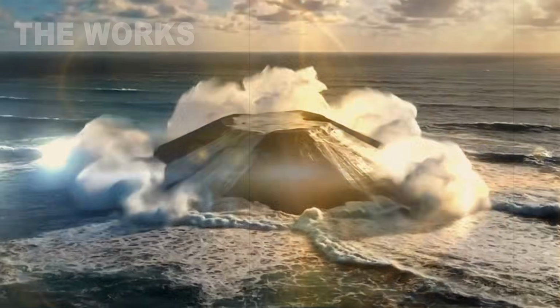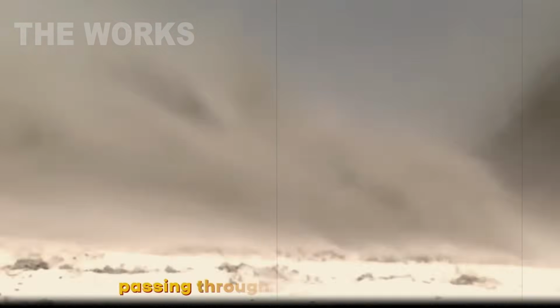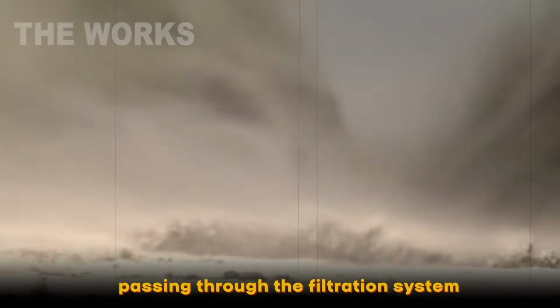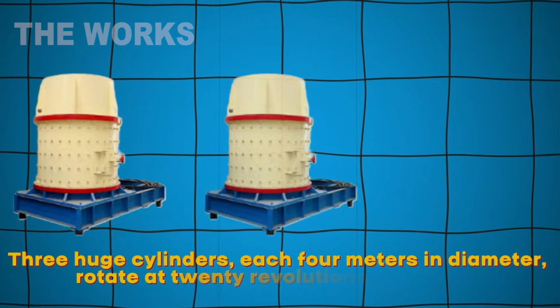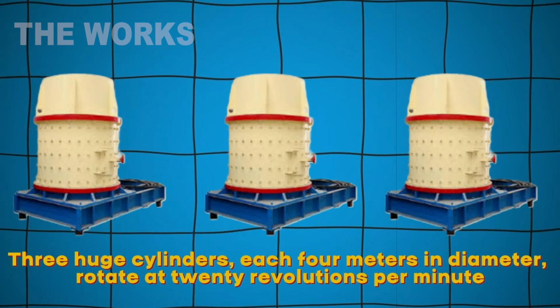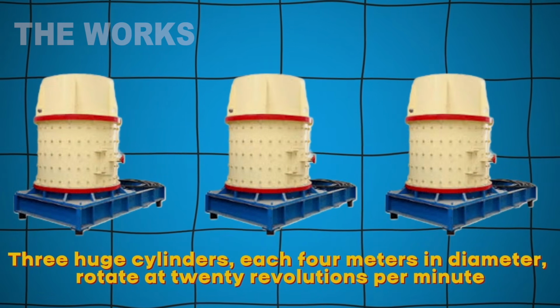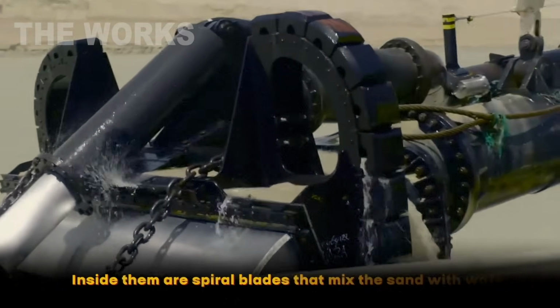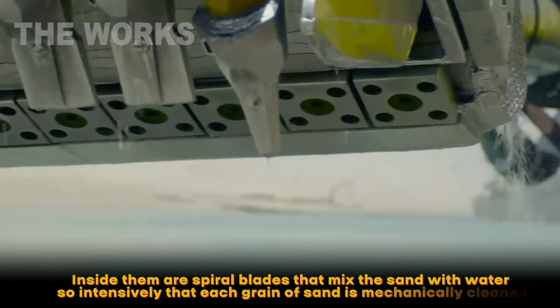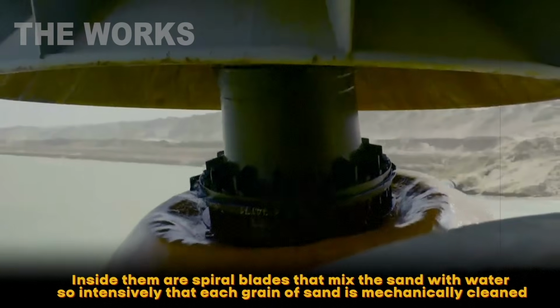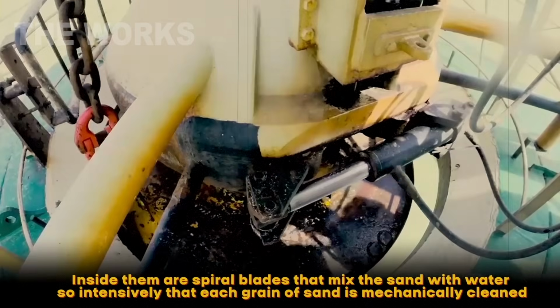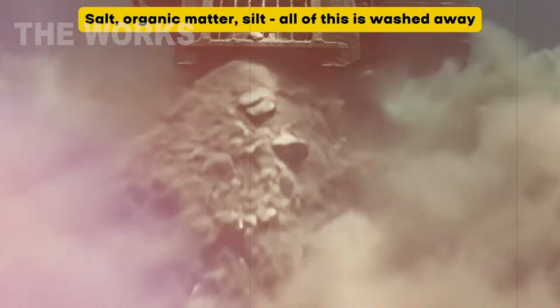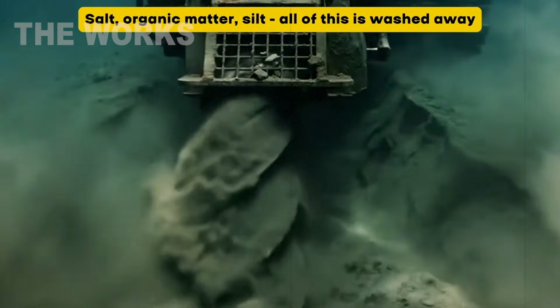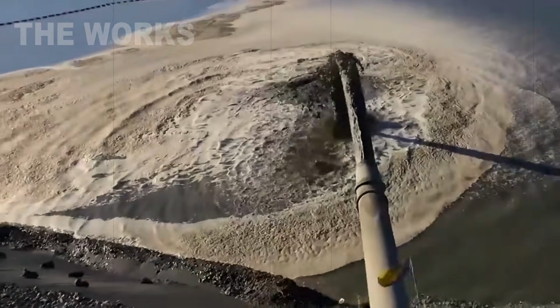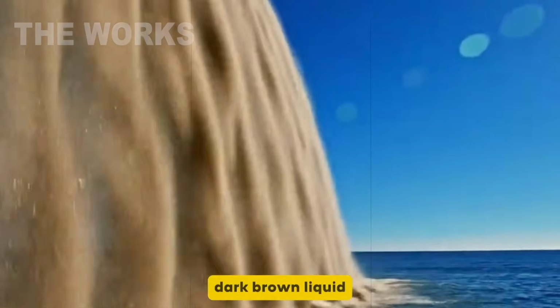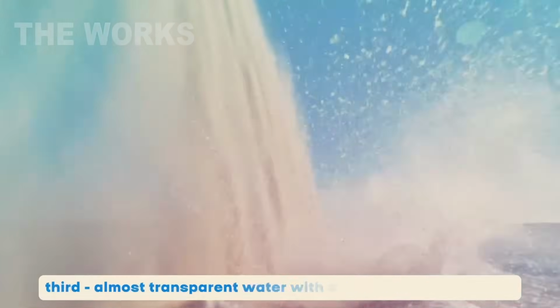The water here is seawater, but it runs through a filtration system. 3 massive cylinders, each about 13 feet in diameter, rotate at 20 revolutions per minute. Inside them are spiral blades that churn the sand and water so intensely that every grain of sand gets mechanically cleaned. Salt, organics, silt, it all washes away. I watch as dark brown sludge comes out of the first drum, light gray from the second, and from the third, nearly clear water with clean sand at the bottom.